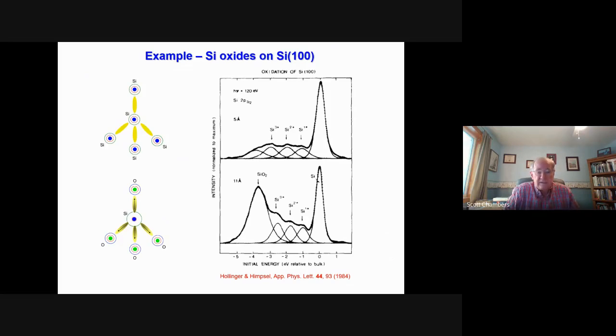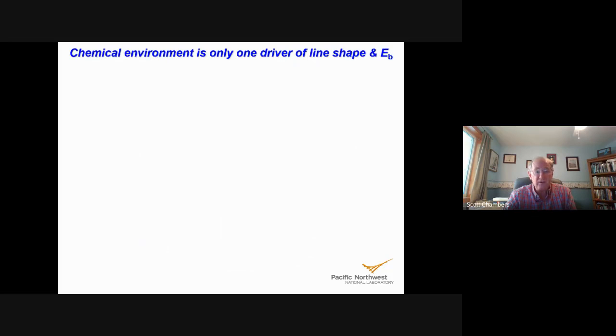And so if you take a look at this classic study by Franz Himpsel, formerly at IBM, what you find is that for light oxidations of silicon, looking at the silicon 2p3/2 peak, which has a binding energy of about 100 eV, you see 4 different peaks there corresponding to the 3 different suboxides of silicon, and then finally SiO2. And so as the formal charge on the silicon goes up, you can see that the binding energy goes up, roughly 1 electron volt per unit change in oxidation state. So this is what everybody understands, and everybody uses this primarily to interpret their data. However, this is not the only driver.